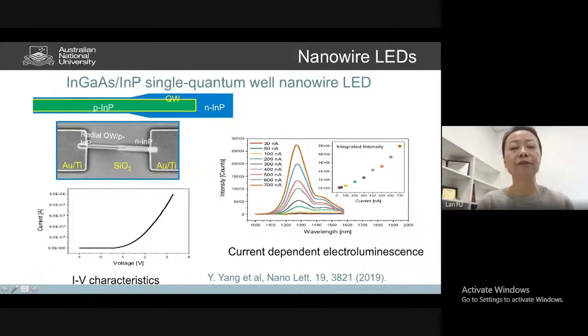So what we do is that we have to do photolithography and electron beam lithography, which is basically a high resolution lithography technique, so that we can actually cover half of the nanowire so that we can do some etching. Thereby, we can really contact the P core, the P-type indium phosphide core, on this side. And then we actually release that, and do some etching. And then after etching, we could actually do photolithography for contacting, thereby